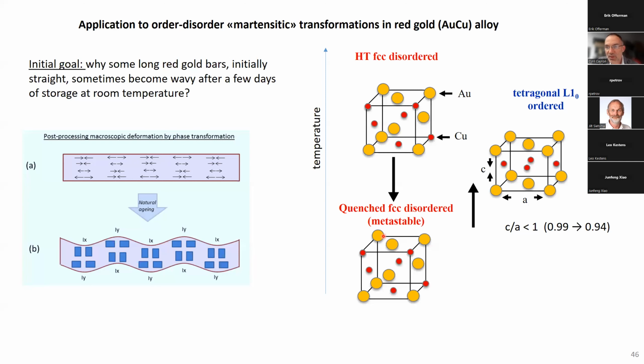I will finish this presentation with a very specific, strange martensitic transformation in red gold alloys. Okay, I work in Switzerland, and we also work with the watch industry, we work on red golds. And we were contacted by companies that wanted to understand why when they make some very long red gold bars, some meters long, they leave the bar a few days at room temperature, and then the bar becomes wavy. They wanted to understand that. So I supposed that it was an effect of a phase transformation. What is a phase transformation in these alloys?